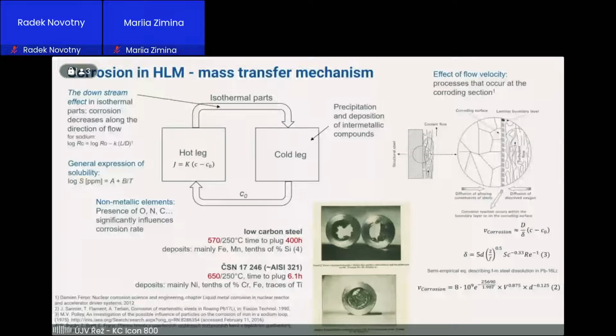So the problem with these coolants is, let's say, mass transfer corrosion. It's a bit different corrosion. It's inherent to all non-isothermal systems. It's based on solubility of steel elements in circulating metal, and you will dissolve some of your reactor in the core and transfer it to the cold leg. And that's the main problem of this system. You can see here one example of low carbon steel at very high temperature. It takes 400 hours to plug with iron, but if you put there some stainless steel containing nickel, then you can plug it very fast.